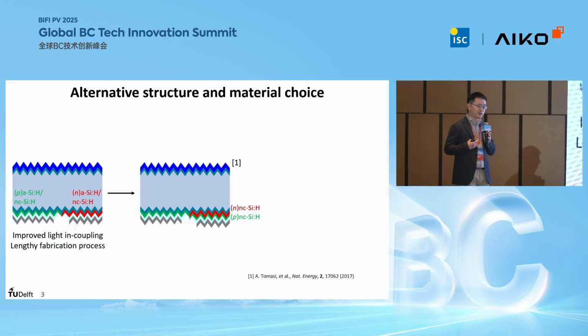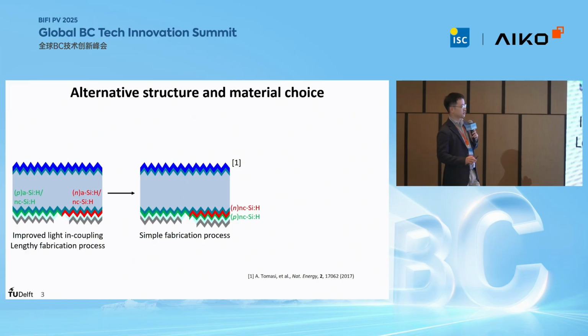To simplify this fabrication process, an alternative concept, the so-called tunnel IBC, features a deposition of a full area P-type nanocrystalline silicon layer on a pre-patterned N-type nanocrystalline silicon layer, forming a tunnel junction to collect electrons through the N and P layer, while the holes are collected on the other side. This could enable a simpler fabrication process. However, due to the high lateral conductivity of the P-type nanocrystalline silicon layer, it might reduce the shunt resistance